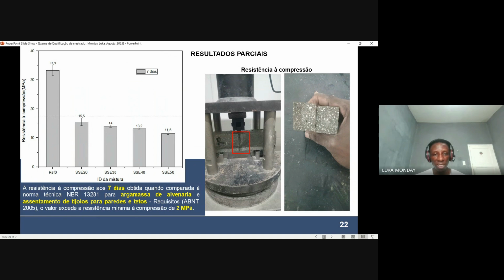On the aspect of compressive strength, as the substitution level increases, the compressive strength decreases. However, this is a 7-day result. Based on the Brazilian standard, which specifies 2 megapascals, all of the substitution levels attain values exceeding the standard. This shows that this material can be used as a structural material, and also as a non-structural material, based on the values attained here beyond the normal standard.